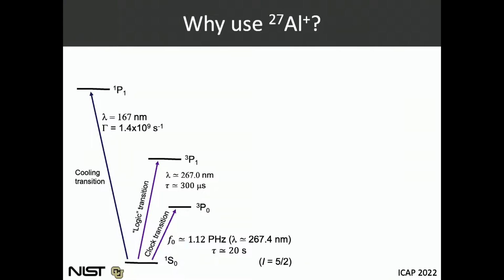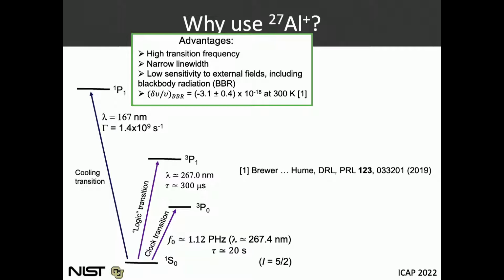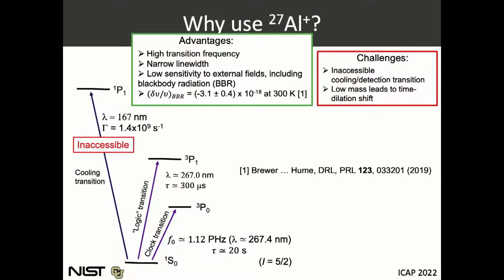At NIST, in my group, we really like aluminum ions for optical clocks, and that's because of this clock transition here between the singlet S0 ground state and the triplet P0 excited state. This is a good transition because it's very long-lived. It has that 20-second lifetime, so we can do narrow line width spectroscopy. It's also really insensitive to the environment. So for example, the blackbody radiation shift at room temperature is a few times 10 to the minus 18. But there is a challenge with aluminum, and that is that the lowest electric dipole transition is in the vacuum ultraviolet at 167 nanometers. So we don't have this laser.